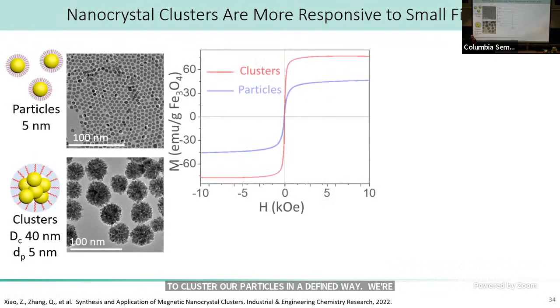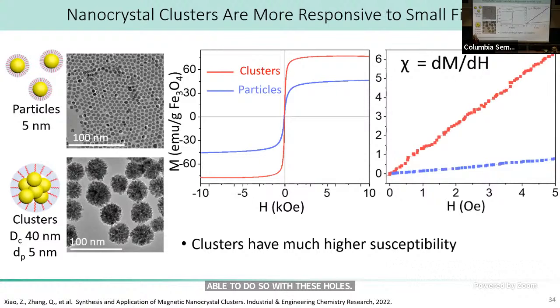I'll get to my applications. And the good news is it's what we would expect. When we make these clusters that have the holes, they're porous single crystals, their susceptibilities are substantially orders of magnitude higher than if you had a single crystal with no holes, and if you had smaller, just a single particle. I'll show you that data now.